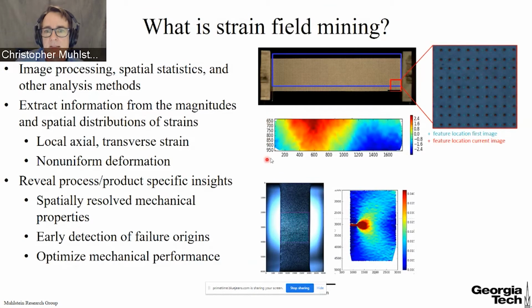And shown in this little heat map below is the distribution of the axial strain. So this is how much it's stretching along the long axis of the paper. And what we can see is this nice red hot spot where the strains are getting concentrated as a byproduct of the local fiber network structure.